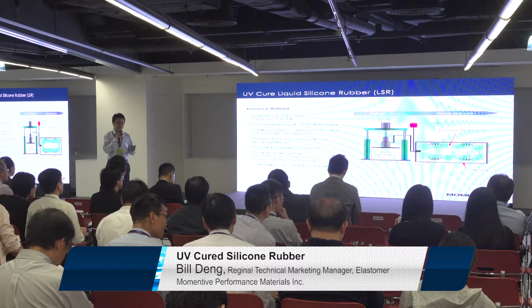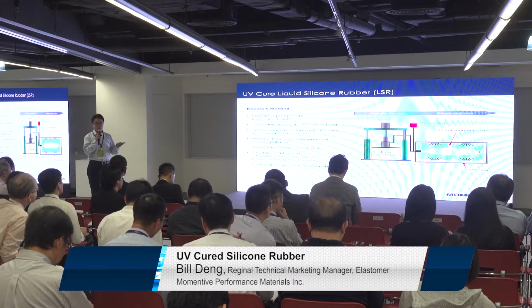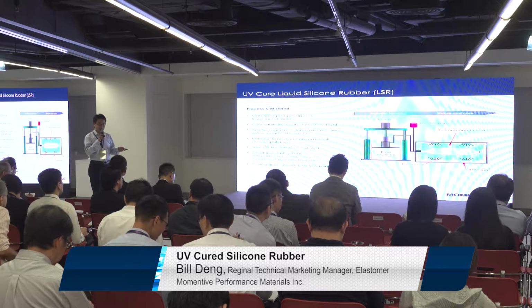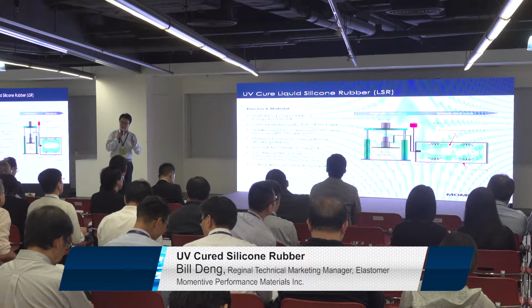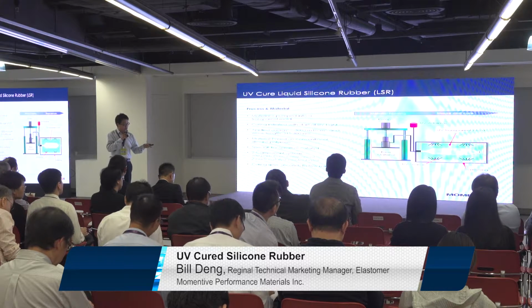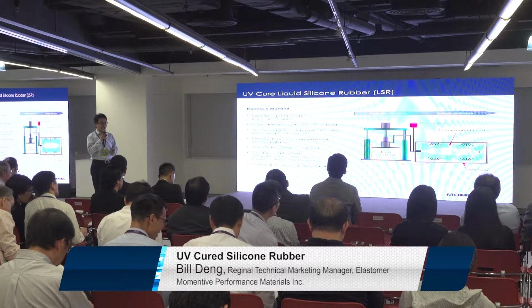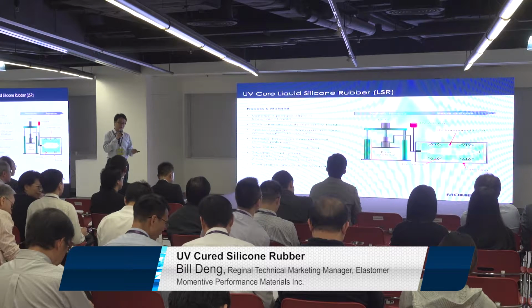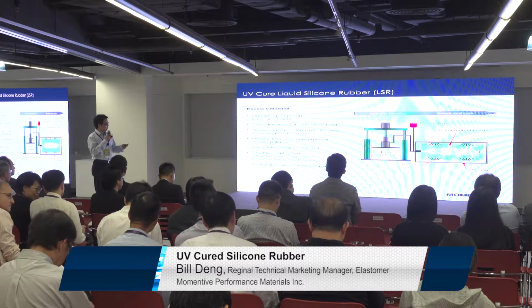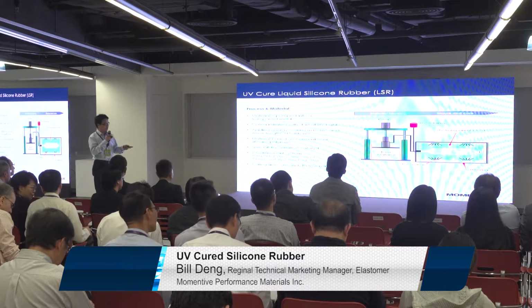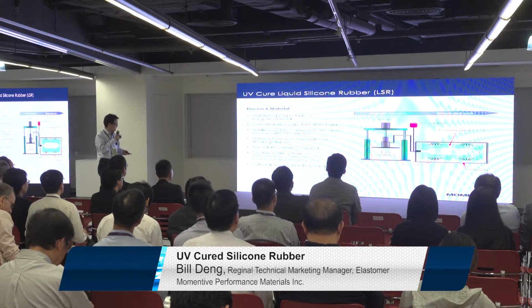Usually we recommend a PMMA or polycarbonate mold as the transparent mold for the curing. Otherwise, the light will be stopped, so it's not good for the curing. That's the difference between the UV LSR and the traditional LSR.